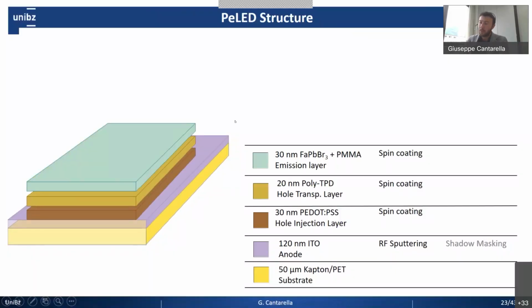The way we realized the perovskite LED was mostly done by the collaborators that we had at ETH Zurich. I suppose the spin coatings are managed in a way to reduce any damage to the successive layers. For example, PEDOT:PSS, I have also been working with this material, and usually as long as you spin coat it and then dry it, removing the solvent, the layer is quite uniform and stable. Whenever you prepare the solution for, in this case, the hole transport layer, you need to make sure that the solvent you use doesn't harm the underlying layer. It's just chemistry that could be optimized, but in my experience, all these layers and the solvents they are mixed with are pretty stable.